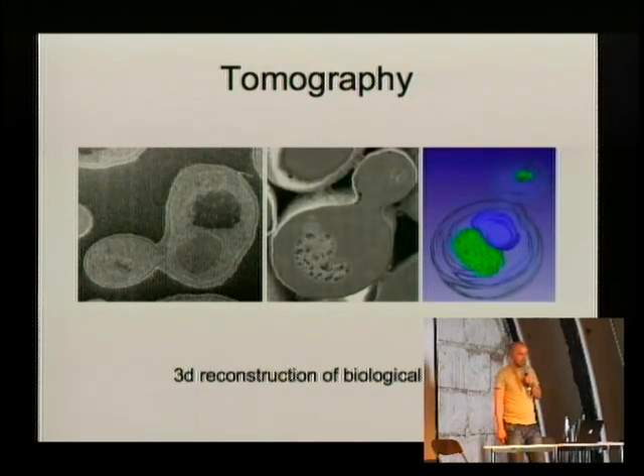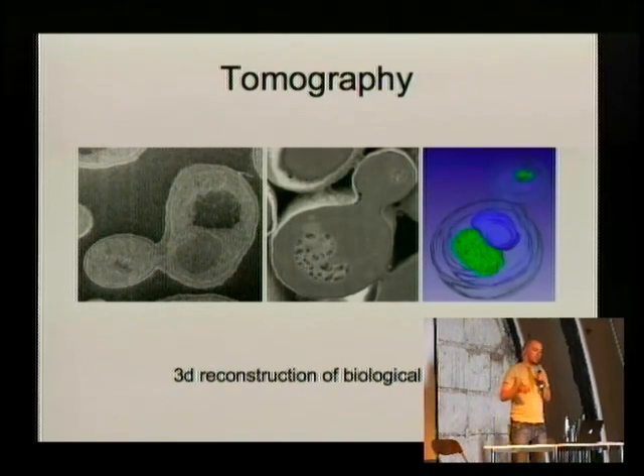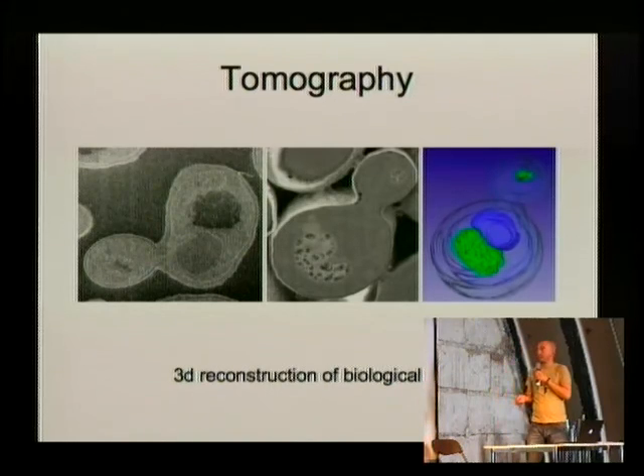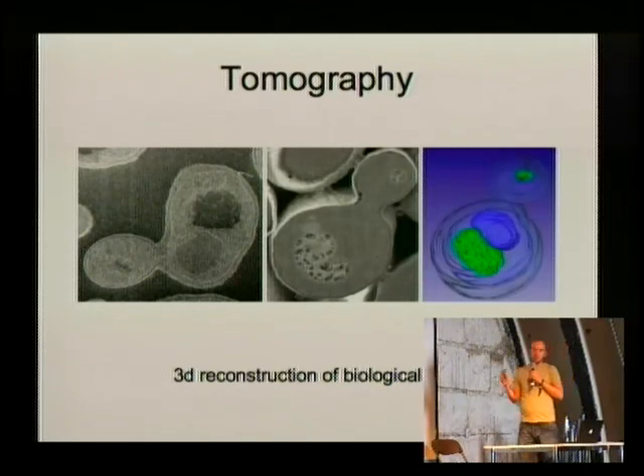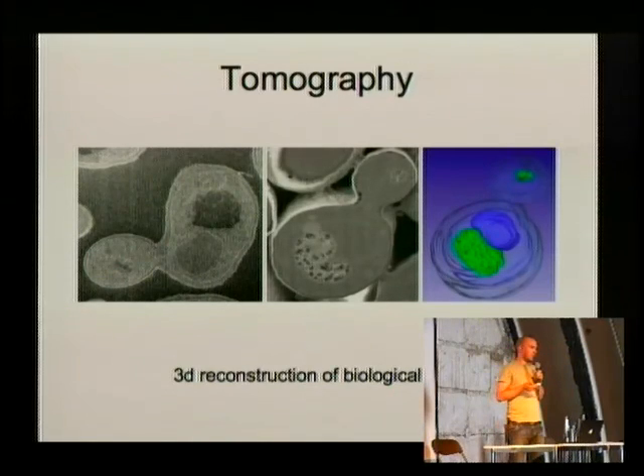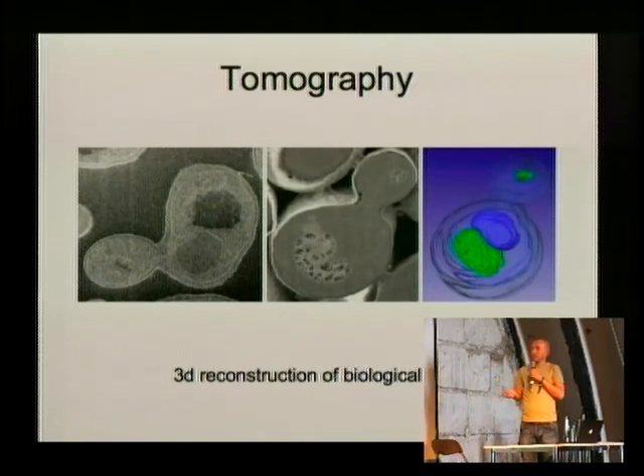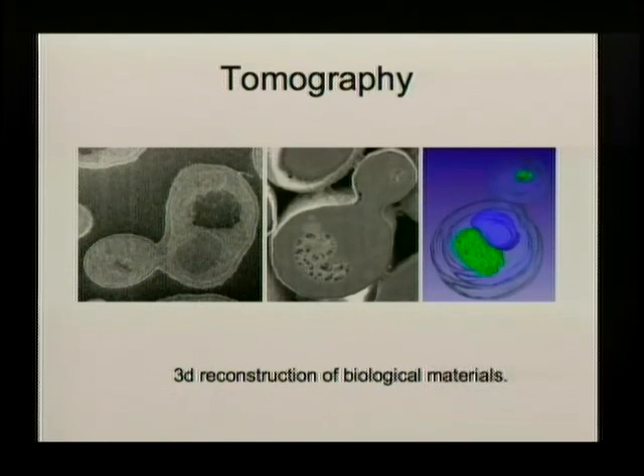Another nice thing is, since you are able to make very thin slices, you can make the slices and after each slice take a picture, then run this series of pictures through the computer and get some tomography or some 3D reconstruction. In this case, that was done on a biological sample. For this, it used to be that the samples had to be prepared in a special way, frozen or embedded into some plastic. But nowadays, even that is not necessary anymore. You can have a certain pressure in the microscope, so you can take not exactly living cells, but almost living cells, cut them apart and look at how it looks on the inside.